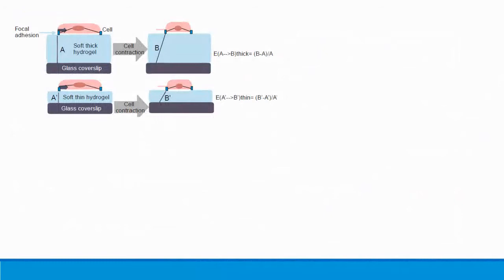We hypothesize that bone marrow stromal cells will spread more and differentiate into osteoblasts on soft polyacrylamide hydrogels when decreasing hydrogel thickness. To test this, we fabricated polyacrylamide hydrogels of different stiffness and thickness. We measured these properties and evaluated their effect on cell spreading, proliferation, and differentiation. And we also evaluated hydrogel deformations.